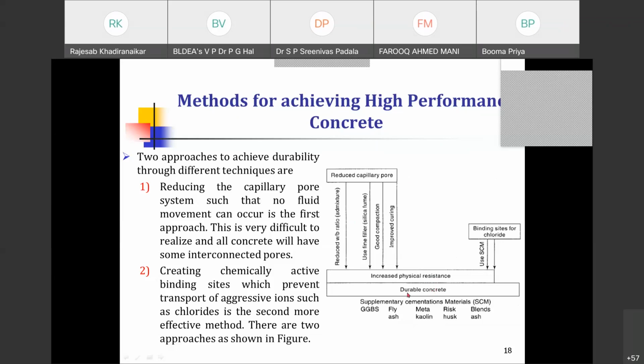And the other technique is creating chemically active binding sites which prevent the transport of aggressive ions, such as chlorides. This is the second, more effective method. These are the binding sites that you are providing. So how are the binding sites provided? That is by the use of SCMs, that is supplementary cementitious materials. It is mandatory, of course, in HPC as well as in HSC. So we are using supplementary cementitious materials, and these provide the additional binding sites wherein whatever calcium hydroxide is released will react with these materials.